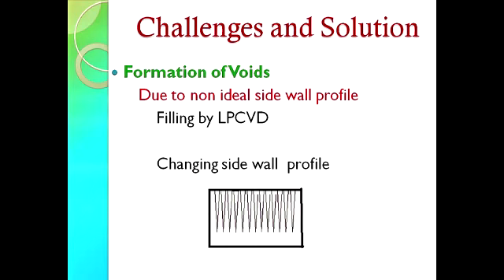So this can be overcome by filling the oxidized wafer with LPCVD for further closure of the voids, or we can also change the sidewall profile like this so that we have pointed trenches at the bottom and wide trenches at the top, so that the bottom trenches are easily oxidized and the top portion can be oxidized by LPCVD, so even this can be used.